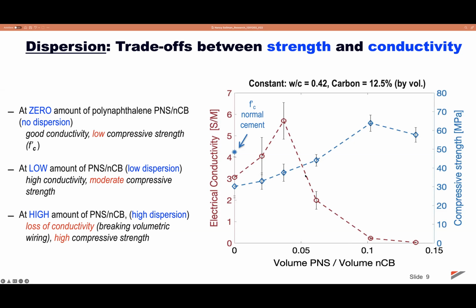And here I will present the effect of polynaphthalene superplasticizer as a dispersant agent in nanocarbon black particles. Here we use a constant water-cement ratio of 0.42 and a constant carbon content of 12.5 percent by volume. In the x-axis, we see the volume of the polynaphthalene superplasticizer divided by the constant volume of nanocarbon black. In the left axis is the electrical conductivity, and in the right axis is the compressive strength